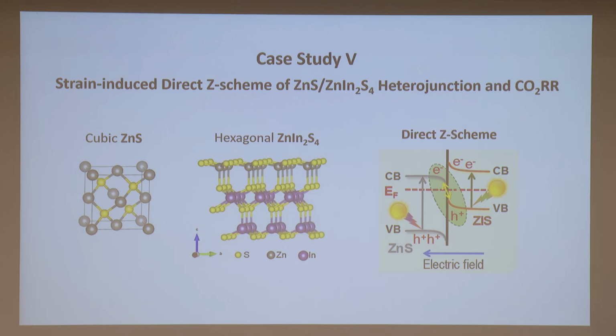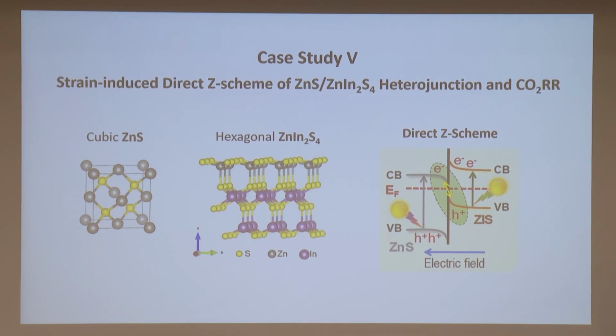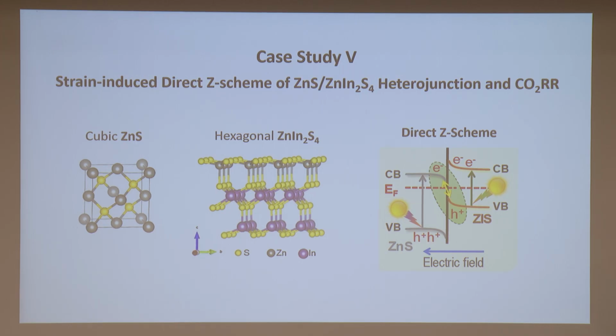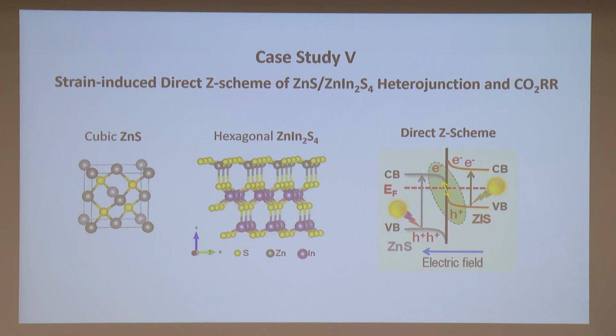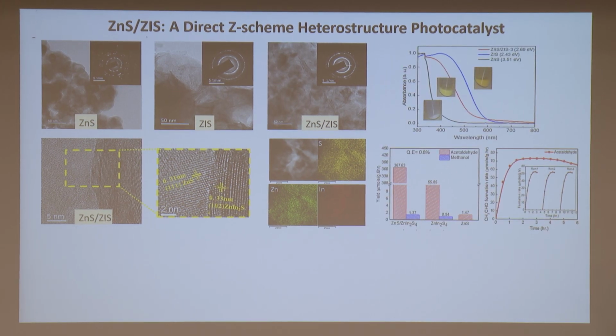But this is essentially playing with heterojunction, charge separation, and light harvesting. Usually, for a very good sample, sometimes it does not harvest light very efficiently. So we do have to have a strong absorber, and for that you couple with another material, you can increase light harvesting and at the same time increase the charge separation. This is the essential idea, and I don't have time to go through it, but by combining zinc sulfide and zinc indium sulfide, we are able to produce a final result of 0.8 quantum efficiency. This is by far the top material in my lab.